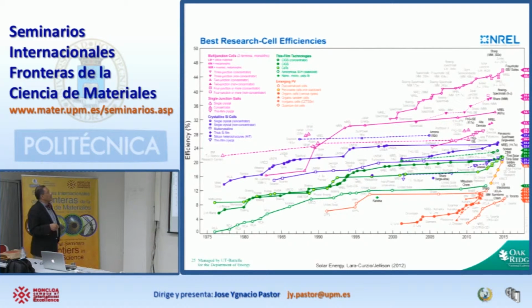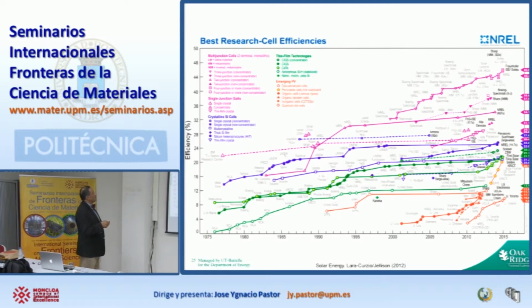Then you have these so-called thin film technologies in green. These include these copper, indium, gallium, selenide. They are so-called CIGS. And you can see how they've improved efficiency as a function of time. These are cadmium telluride, the ones with yellow. Okay, these are thin film technologies. And again, you barely make 20%. The advantage of these thin film technologies is they are less expensive than silicon.